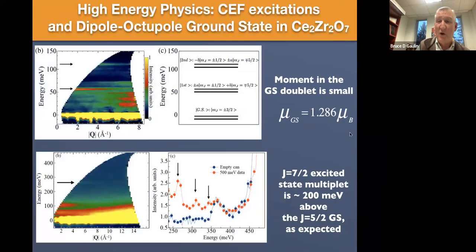So at any rate, all of that is to say that this eigenvalue problem can be solved to within some accuracy experimentally, and it's all done with neutron scattering. And so it tells you what the magnetic moment is in this ground state. It tells you the wave function, and it turns out that for this particular problem, the wave function associated with this pseudospin 1/2 degree of freedom is very simple. It has a single JZ component of J = 5/2, and that's MJ = ±3/2. So that's very simple and also very high symmetry.